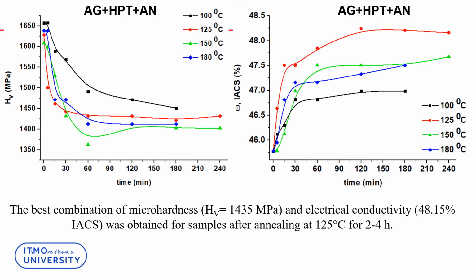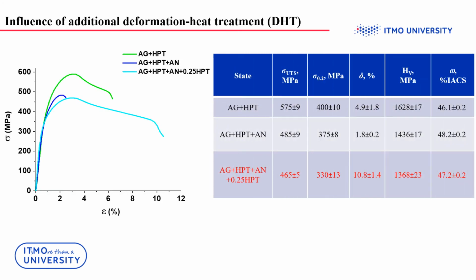In order to obtain optimal annealing parameters, the study of annealing kinetics was carried out. It was found that the best combination of microhardness and electrical conductivity is achieved after annealing at a temperature of 125 degrees Celsius for 2-4 hours. This state was chosen for the tensile test. As we can see, the state after additional annealing demonstrates still a good tensile strength, about 485 megapascal, but very low ductility, less than 2%.